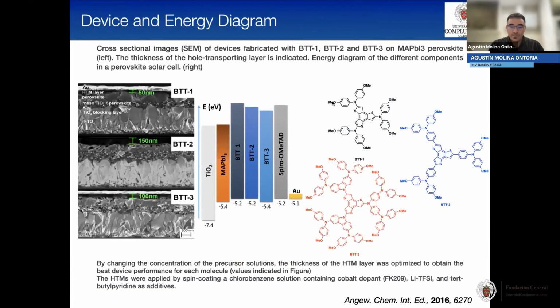Well, we sent these molecules to EPFL, to Professor Nazeeruddin's group, and they made the devices for us. And you can see here the cross section of the device. We can modulate the thickness of the hole transporting layer just by optimizing the concentration. So for example, the best thickness for BTT1 was close to 50 nanometers. For BTT2, it was 150, and for BTT3, it was around 100 nanometers.